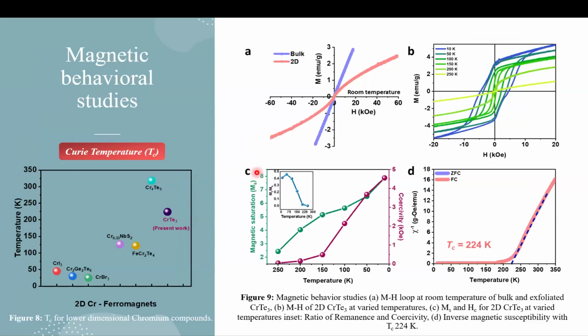So as for the magnetic behavior studies, in bulk, we do not observe any hysteresis. And when we move to the 2D dimension, at room temperature, we see that it has a ferromagnetic nature, and we tested this at different temperatures as well. And as compared to the existing 2D chromium compounds, which have a Curie temperature around 150 to 200, our material had a little higher Curie temperature. So the transition depends on how the synthesis method was used.